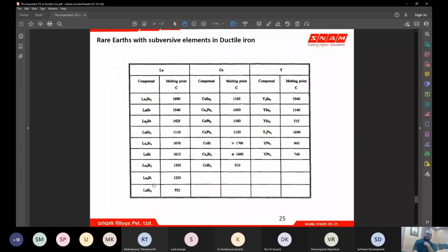rare earth elements can form, such that you see all these elements are formed at a very high temperature, and it does not let anything come into your liquid metal during solidification. Rare earths will help you to counter the tramp elements present, such that it forms compounds which are higher than the melting point, and it has another advantage that these compounds formed are getting converted into heterogeneous nuclei. So rare earth has direct cerium or direct lanthanum giving you nuclei. Also, it reacts with the subversive elements and converts that into useful also.